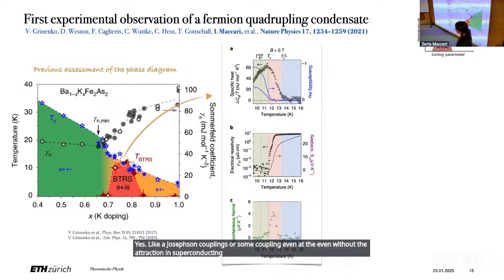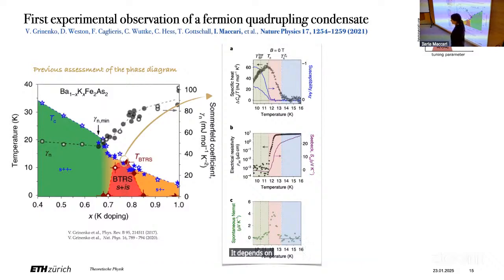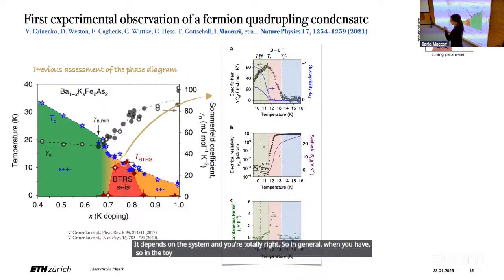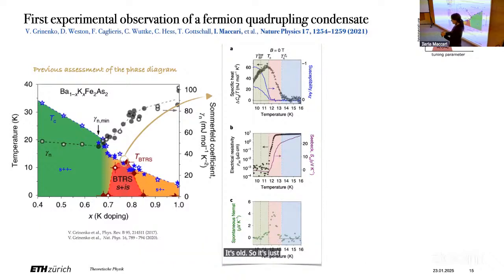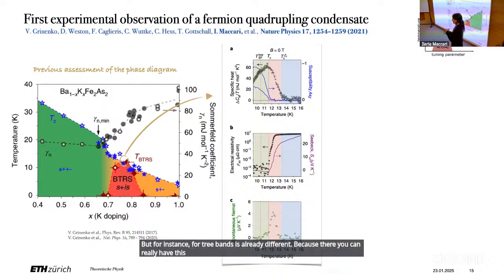So this phase is not really spontaneously broken. It depends on the system, and you're totally right. In the toy model I showed you, there was a huge missing term, which was this Josephson coupling, right? That is typically there when you consider a two-band superconductor or two components. So you have this term that locks the phase, so there is no mode at all. It's just a locking between the two phases. But for three bands it is already different, because there you can really have the emergence of frustration, right?